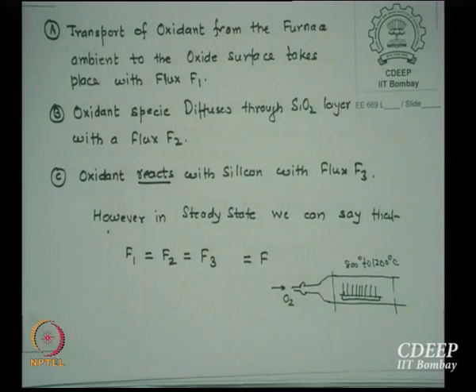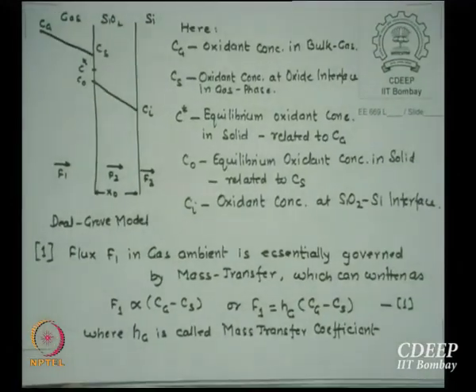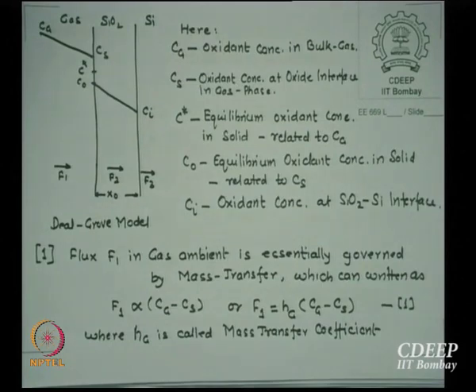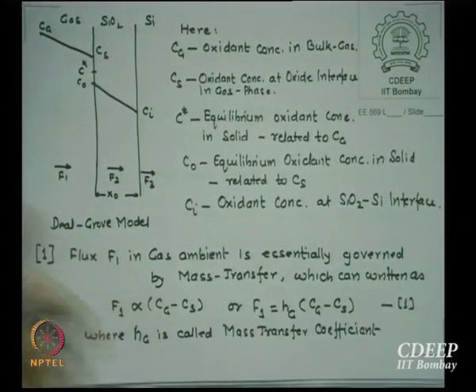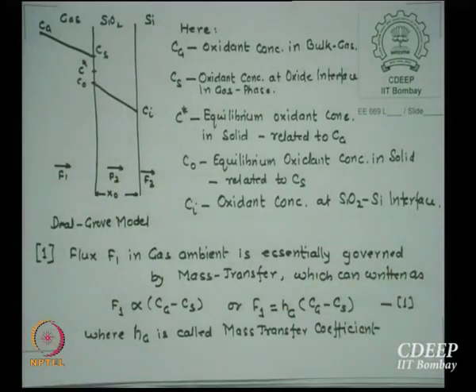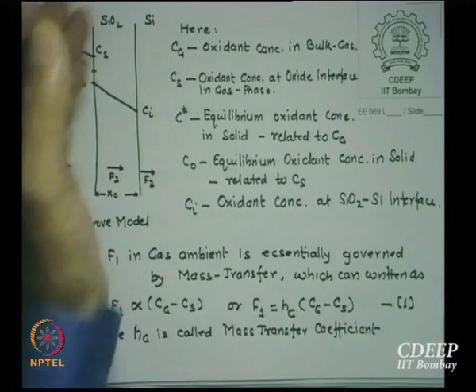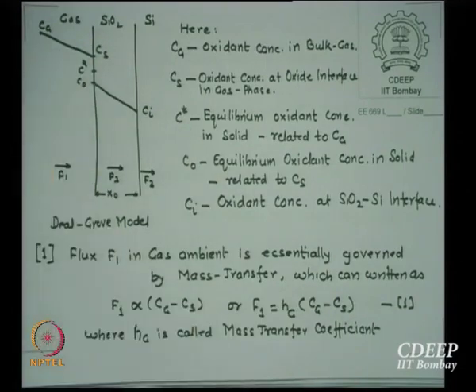So let's start with the model. This is what we did last time. Now we actually look at the model. Okay, here is the model. Same thing as what I wrote, but there are now a few more definitions. Let us say Cg is the oxidant concentration in the gas stream, not near the surface but inside the whole tube. Then corresponding to this Cg, we have an oxidant concentration at the oxide interface, Cs. There is a gradient from Cg to Cs because there is not enough oxidant near the surface.